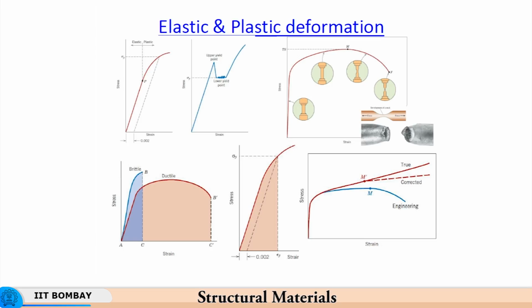Now, we have seen in strengthening mechanisms that the work hardening is because of one dislocation blocking the other, or when there is a high dislocation density, the dislocations themselves impede the dislocation movement, and therefore that helps in work hardening. But then once the dislocations have arranged themselves in low energy configurations like subgrain boundaries, then the hindrance to the moving dislocations is reduced. The extent to which the dislocation can move freely without being obstructed continues to increase, and therefore, the load carrying capability of the cross section decreases,